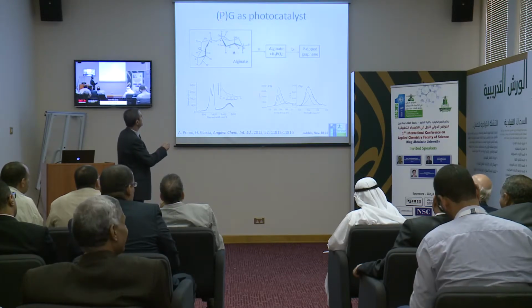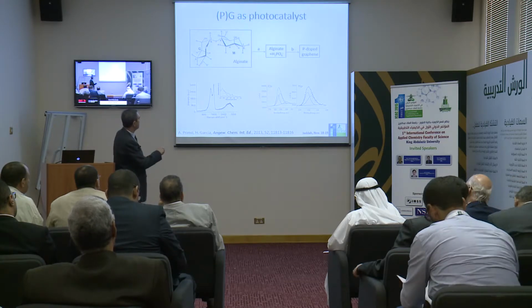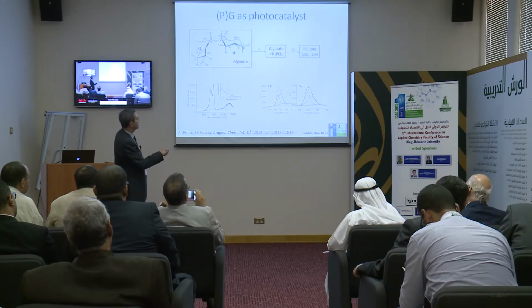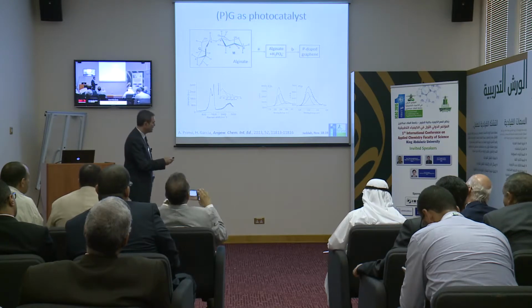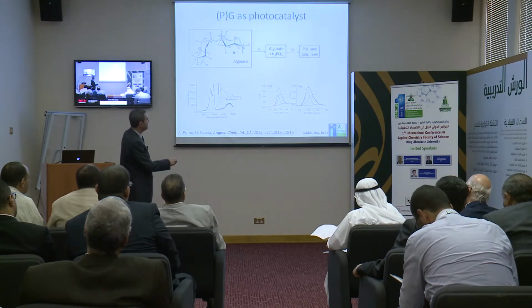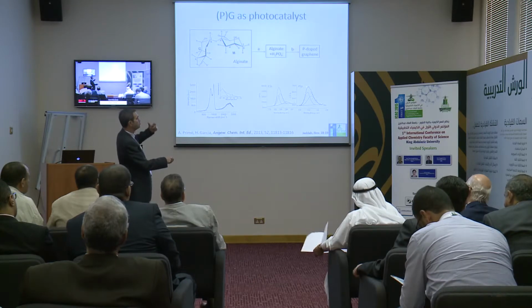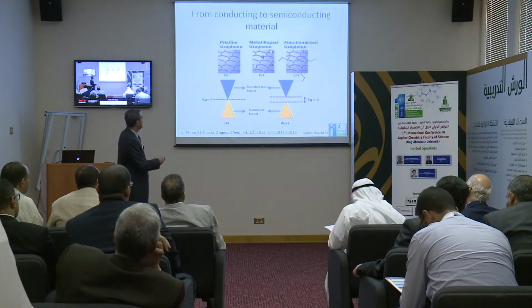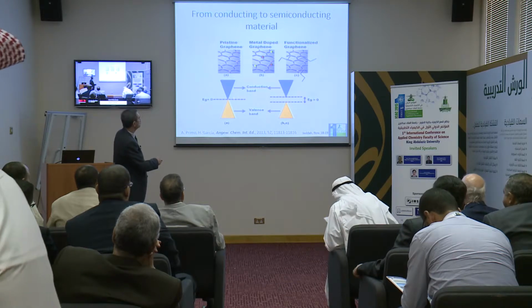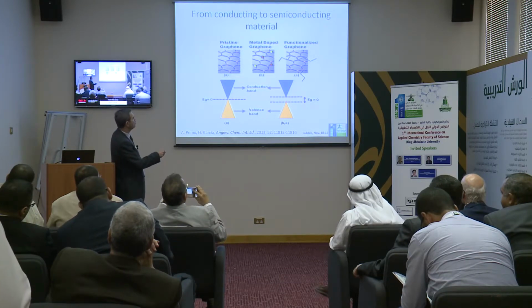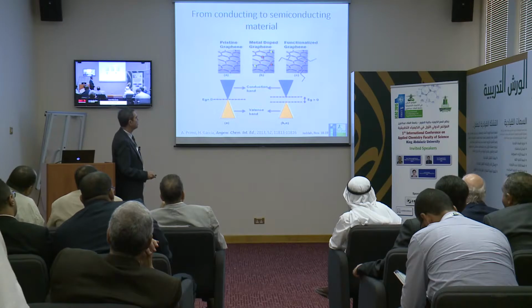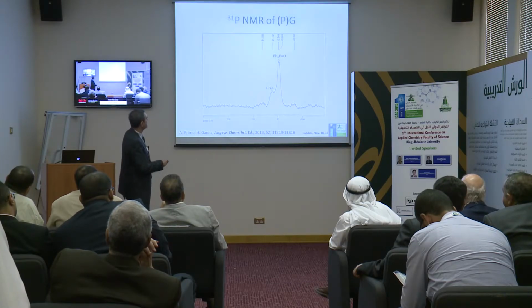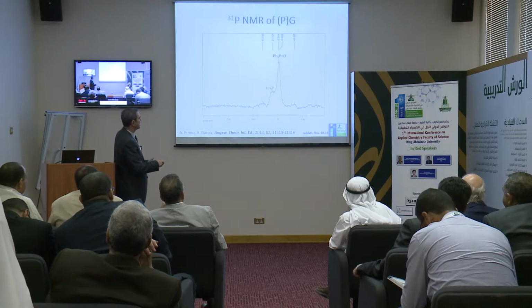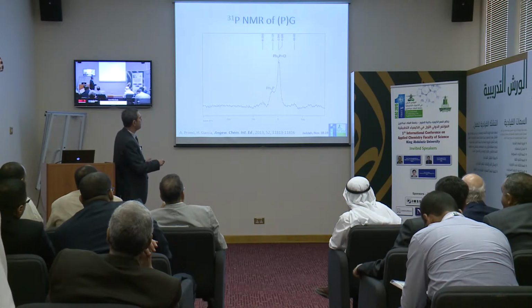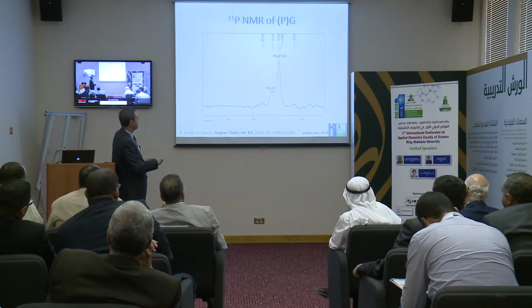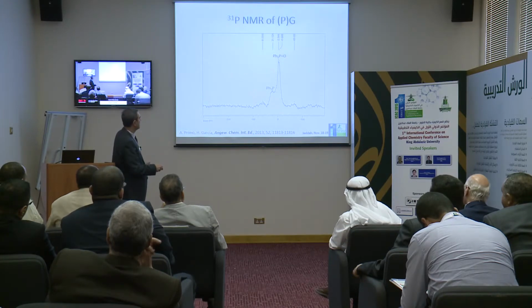So then with this doped graphene, we have prepared by pyrolysis of alginate. This is the phosphate ester of the alginate, and we have phosphorus doped graphene. This is the evidence that graphene contains some phosphorus incorporated into the layer. And then graphene becomes from conductor to semiconductor, and we can use this phosphorus doped graphene to do photochemical reactions. This is the phosphorus NMR, showing that we have in the graphene 2 different types of phosphorus, one that is similar to the phosphine, and another that is similar to phosphine oxide.